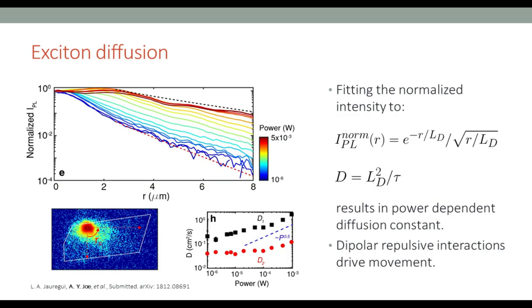So we did a power dependence, and we radially averaged how much the exciton counts are increasing with R. If you look at the lower left panel, we essentially averaged over this 90 degree area, and as a function of power, what we can see is that the slope on a semi-log scale changes with power. If you solve the radial diffusion equation, you can get a dependence of the diffusion length on this slope on the semi-log scale, and from this we can get a diffusion constant.